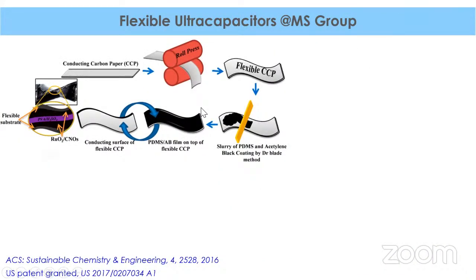This was developed by one of my students. His entire PhD thesis was on flexible ultracapacitor development. What he did was take commercially available conducting carbon paper, which we generally use to test the electrode materials that we have developed. We coat the material on this conducting carbon paper and make an open cell to test these electrodes. Instead of doing that, he took this conducting carbon paper and mechanically pressed it through a roll press at room temperature.